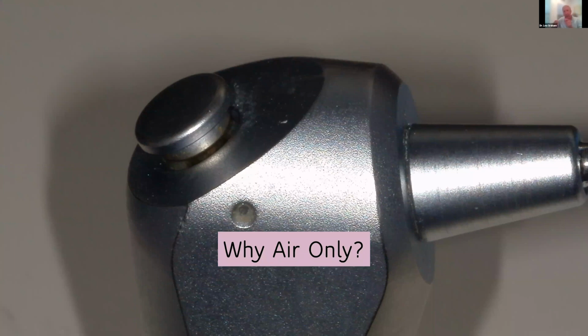So you're going to air. And when I air, I start at a distance for about 5 seconds, and then I come closer. And then I hit it a little harder. So soft to hard. That's what I would recommend. So you've etched, you've applied your bonding agent for 20 seconds, and that is the air technique.